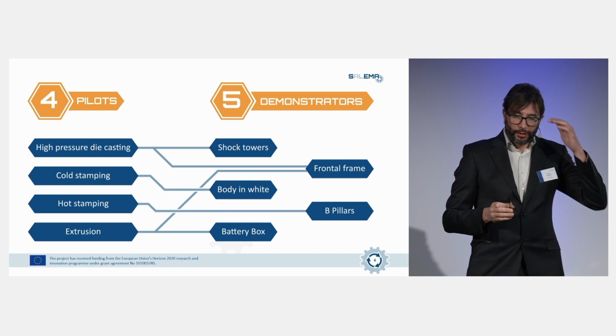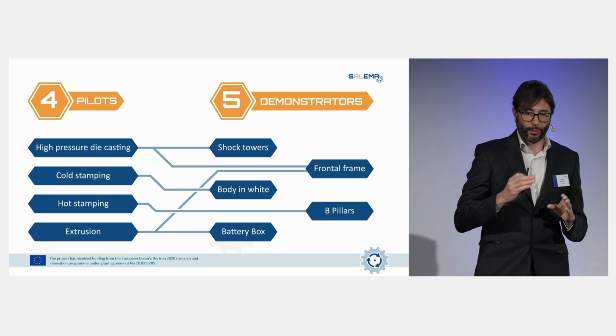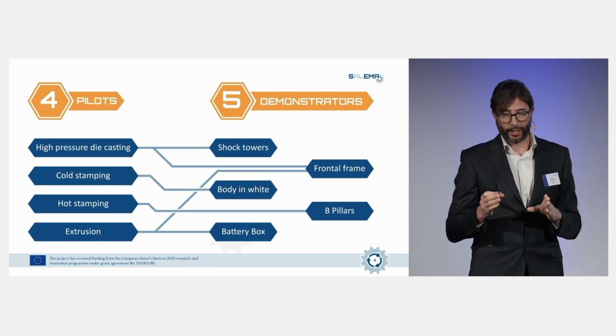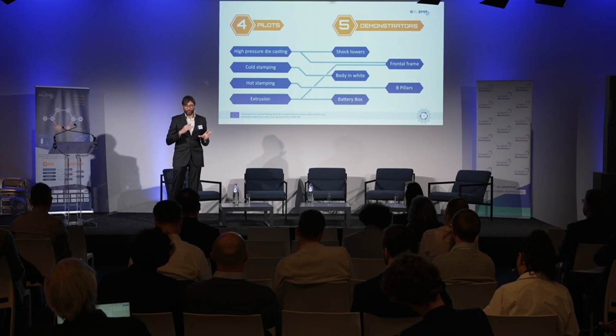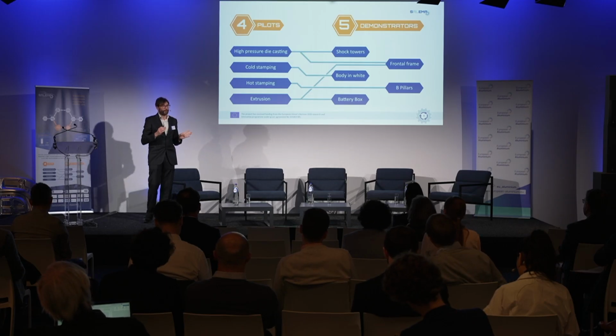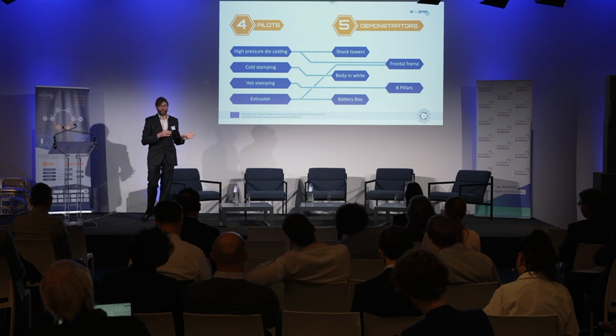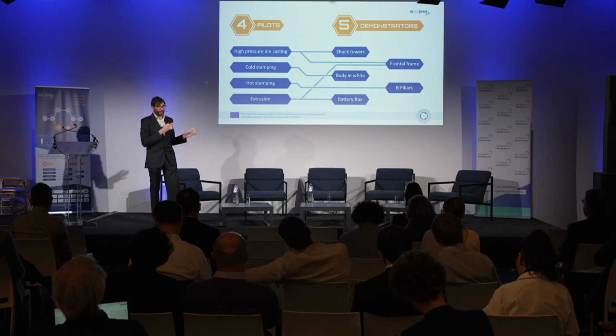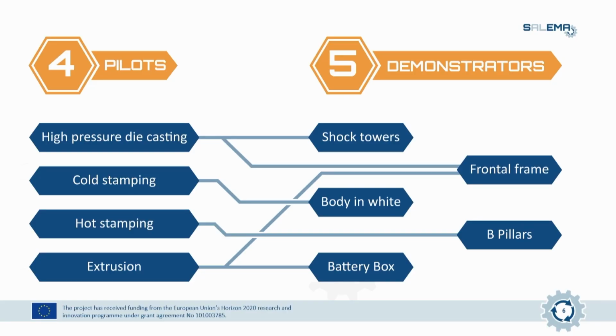And for that, in SALEMA, we target 3 different processes: high pressure die casting, cold and hot stamping, and extrusion, that cover about 95% of the aluminum present in a car. Roughly something like that is produced by one of these 3 processes. And we have used 5 different demonstrators to validate the newly developed alloys. Shock tower produced by high pressure die casting. Also, frontal frame, that is a mixed component. It has one part produced by high pressure die casting and another part produced by extrusion.